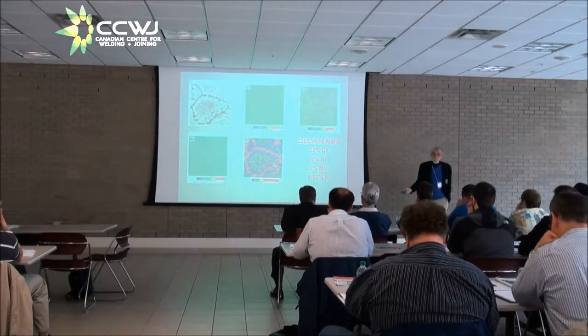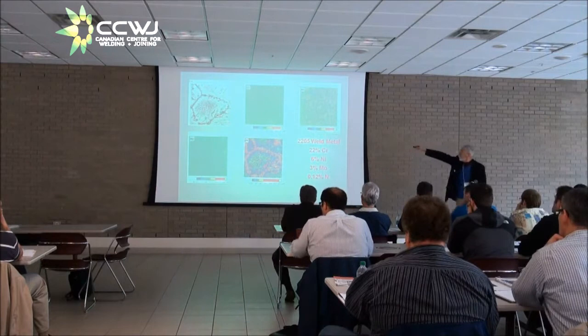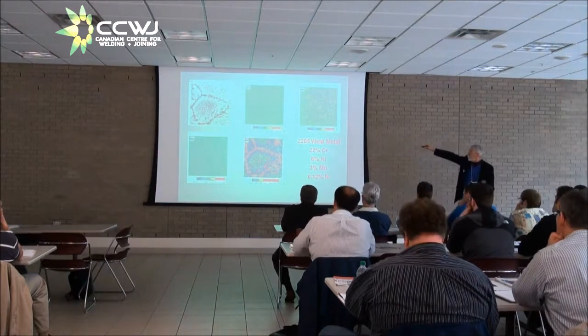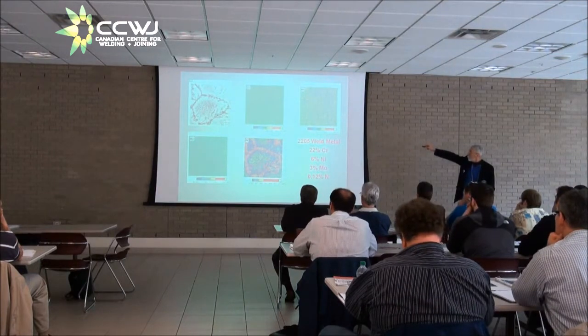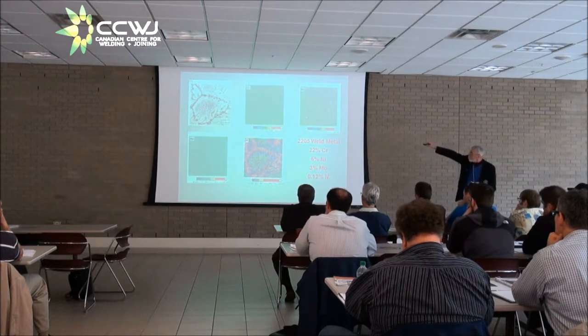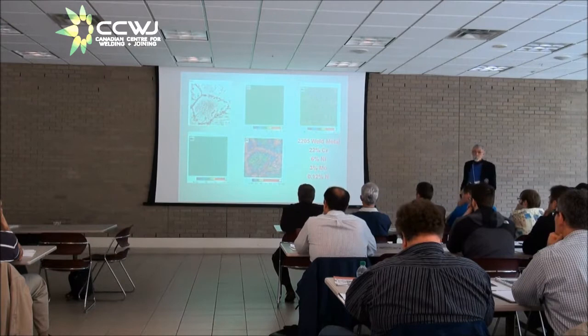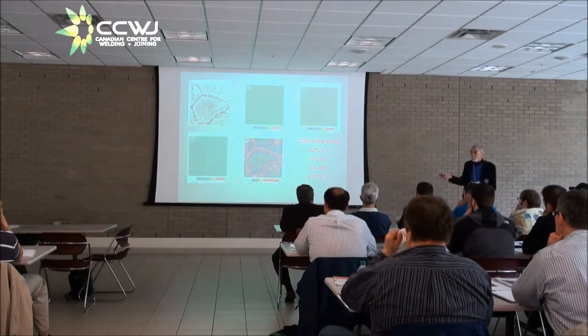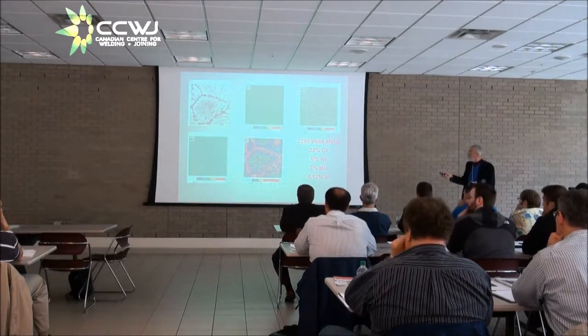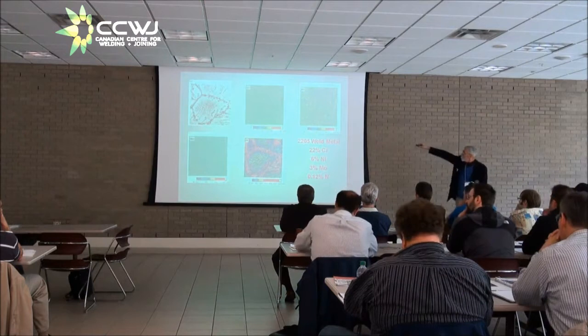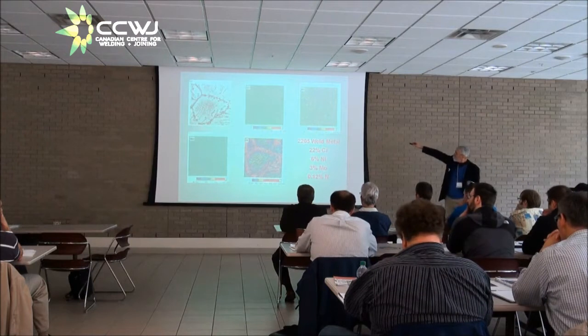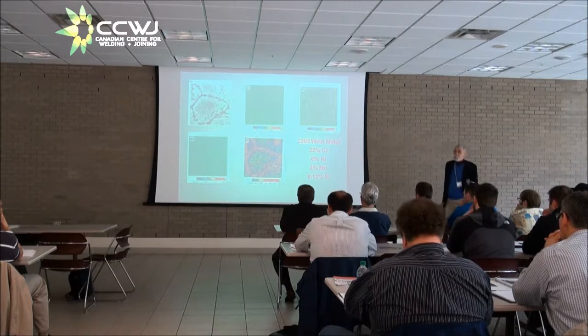When you look at the microstructure in the upper left corner now, what you see is a big ferrite grain outlined by little plates of austenite on the grain boundary. And then in the center of the ferrite grain, there are all these black specks, the chromium nitrides, which I think Ellen showed this morning. And if you look very closely, you can see next to the austenite plates along the grain boundary, there's an area that's clean, doesn't have black specks, no chromium nitrides.